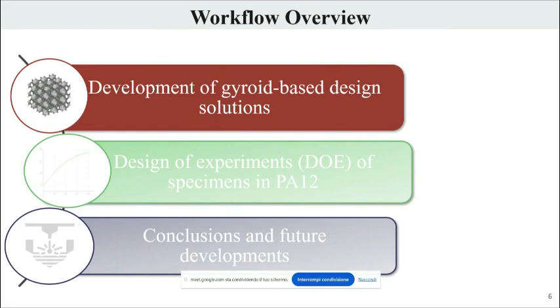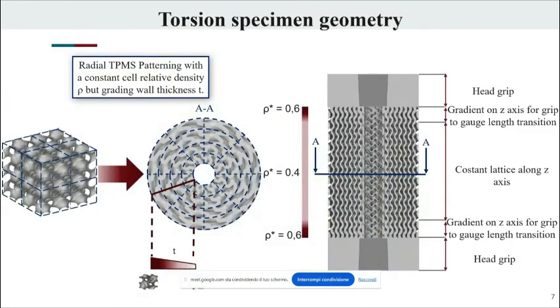Okay, let's talk about the design. Here I'm showing the gyroid-based specimen. It has a cylindrical shape with a radial patterning. We imposed two different gradients of wall thickness. The first one can be seen in the A section, in which the wall thickness is varied from the center of the cylinder toward the outer surface of the cylinder in order to maintain a constant relative density.